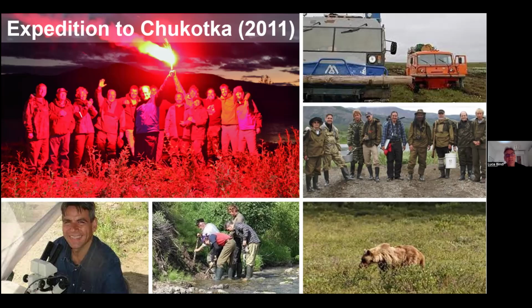During this expedition, we found 10 new fragments, very similar to the Florence Museum sample. All these samples contain copper-aluminum alloys. Not all the samples contained quasi-crystals, but some did, and all the samples contained copper-aluminum alloys with the same characteristics and features as the Florence samples. All the samples collected during the expedition were studied by a combination of different techniques, including scanning electron microscopy, electron microprobe, transmission electron microscopy, focused ion beam technique, and a lot of other techniques.